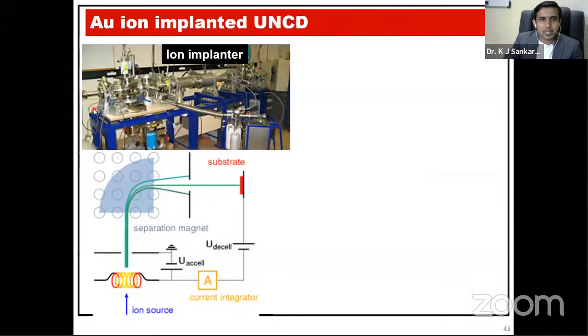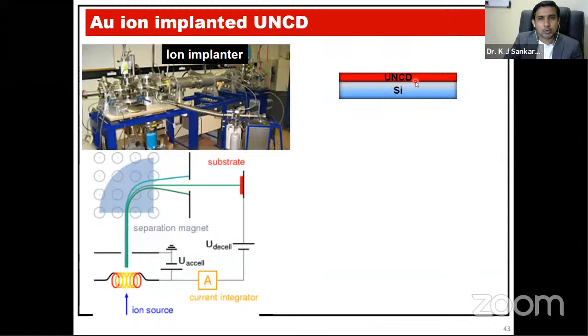So this is the ion implanter at Indira Gandhi Centre for Atomic Research, Kalpakkam. We had a collaboration with Dr. B. Sundravel there, and we made gold ion implanted UNCD. So these are UNCD films grown on silicon. This is not nitrogen UNCD. These UNCD films were grown in methane and argon plasma.